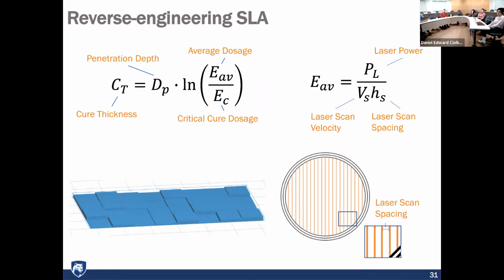And then the dosage, that's the number of photons you shine. So imagine a bright light has many photons coming out, and a dim light has few photons. That's the difference in brightness, right? It's the number of photons. So here the dosage is the number of photons, and the penetration depth is how far they travel inside the liquid. And these are very important parameters for 3D printing because if, for example, your material is opaque and none of the photons can penetrate, then the polymerization doesn't take place and your print fails because it doesn't harden.